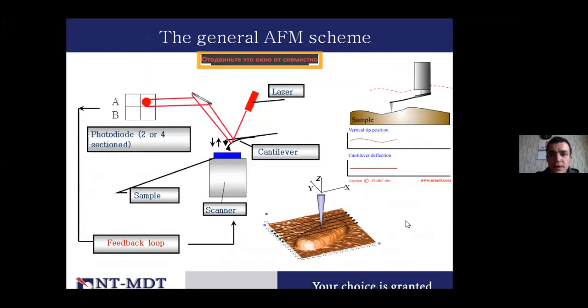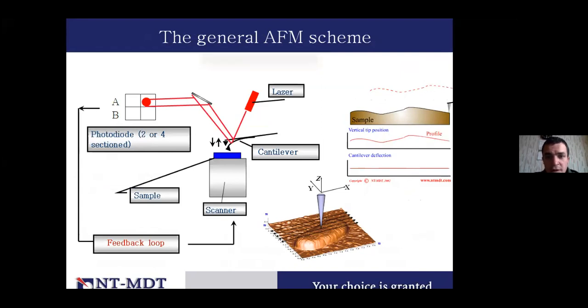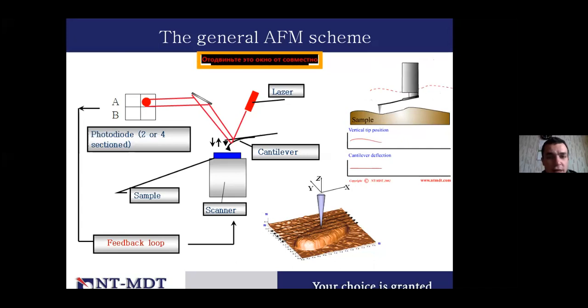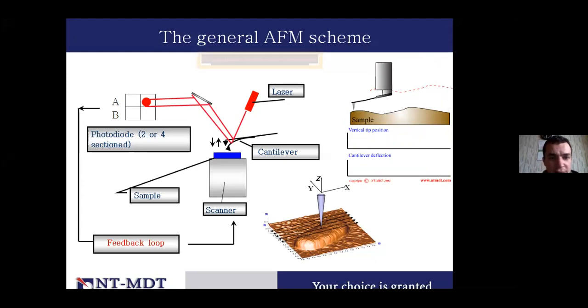Okay, here we switch more to the atomic force microscopy principle, and you can see the basic scheme of how the general atomic force microscope works. In the center we have the sample, which is blue. Under the sample, for example, we have the scanner, which moves our sample left, right, and up, down. From the top of the sample, we have the cantilever, which can deflect depending on the force interaction between tip and sample. Then you can see the laser from the right, which comes to the cantilever, and the reflected beam goes to the photodiode, A B. From the displacement of the laser spot on the photodiode, we can understand what is going on between our tip and sample.